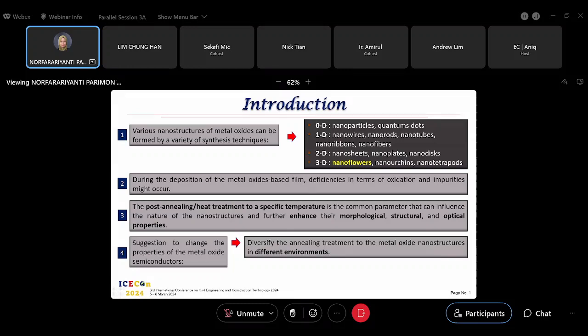In three-dimensional form. During the deposition of the metal oxide based film, metal oxide can be film based or powder based. Deficiencies in terms of oxidation and impurities might occur. So after the deposition of metal oxide, we have to anneal or calcine the sample. The post annealing or heat treatment to a specific temperature is the common procedure that can influence the nature of the nanostructures and further enhance their properties in terms of morphological, structural, optical, electrical, and mechanical as